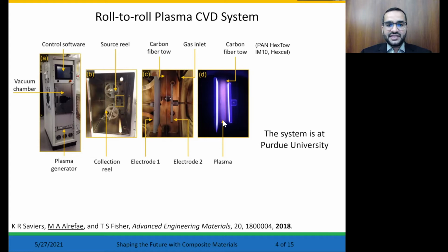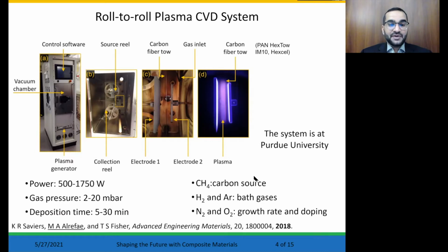Vertical graphene is deposited in the plasma region because of high plasma gas temperature and abundant active carbon species that accelerate the deposition process. The system has 8 input parameters that can be tuned for vertical graphene deposition. These parameters include gas pressure, plasma power, the growth time, and gas mixture of methane, hydrogen, argon, nitrogen, and oxygen. We implemented a design of experiment approach to optimize vertical graphene deposition to reduce the manufacturing cost and time by selecting the most likely operating conditions which can yield high quality graphene.